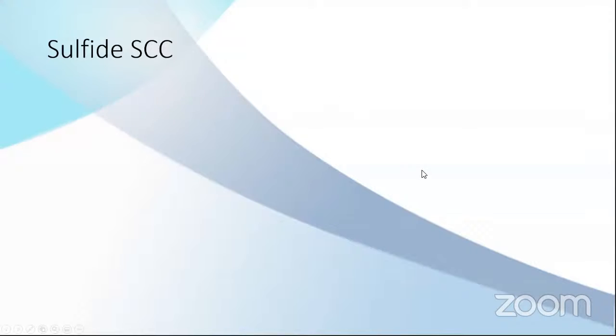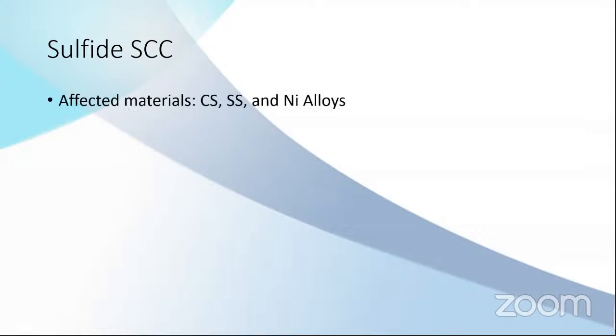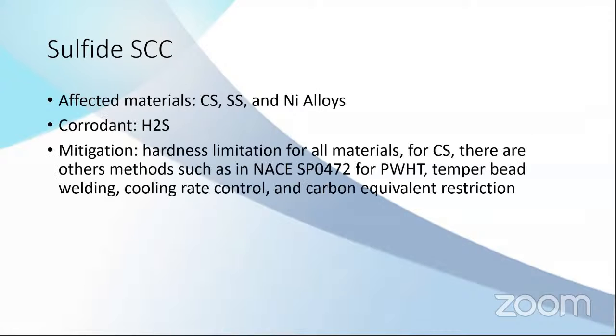I think this is the last one: sulfide stress corrosion cracking. This happens a lot in the oil and gas industry, where you have H2S. All materials are susceptible and can crack. Carbon steel, stainless steel, nickel alloys, they can all crack. The corrosion agent is H2S. The mitigation is to limit the strength.